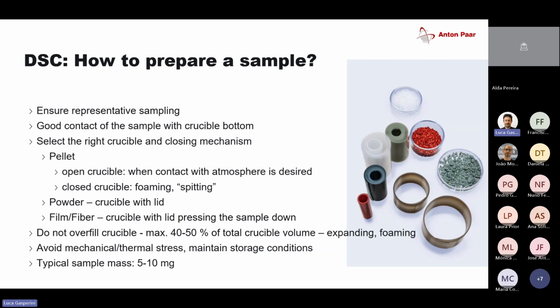In polymers, we might very often have samples in the shape of film or fiber, and these samples are very prone to actually change their shape and dimension as we heat them. They might actually shrink or expand, meaning that I would lose the contact with the crucible bottom. So there we also have some nice things we can do: compress the sample down into the crucible by putting a lid and compacting it down, meaning that the mechanical movement is not going to affect my measurement.